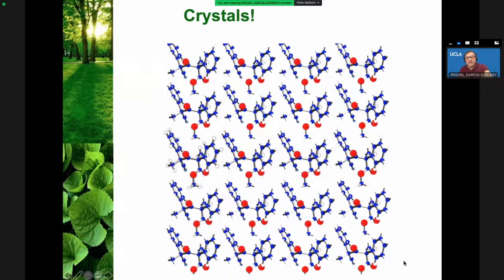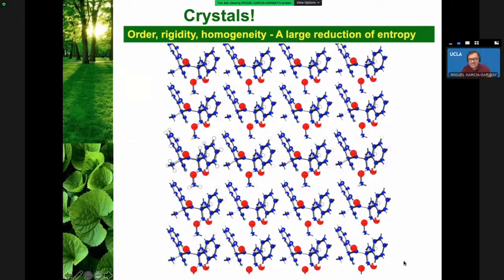Now, if we think about it, the one thing that is probably most general and most common to most crystals, especially molecular crystals, is that they're characterized by molecular order, molecular rigidity, and molecular homogeneity. That is, there is a very large reduction of entropy. If you imagine the total entropy of a liquid, when you have an innumerable number of configurations, conformations, collisional states, normal modes, etc., the entropy content is very high. And when that liquid crystallizes, everything collapses into a single structure, and the total number of states that are available in that structure are significantly reduced. So the first thing to recognize is that there is an enormous reduction of entropy.